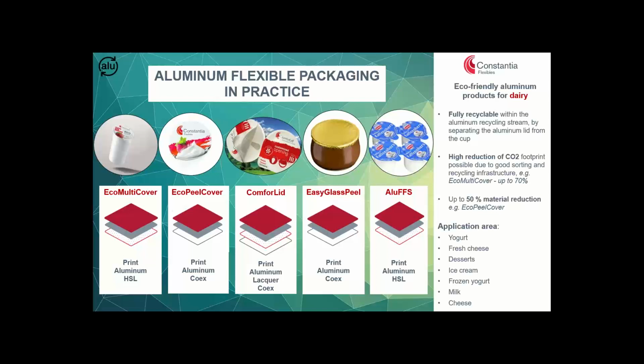So the Eco Multi-Cover is a product that has a thickness of only 30 µ, and it comes with only 4 grams of heat seal lacquer. It has very good sealing qualities against different sealing partners, so this means we have a wide sealing window here. Material reduction, as I said, is a very strong benefit here, whilst retaining the optimal functionality. It runs on conventional filling lines without machine modification. It's also suitable for toppers. Sealable against PS and PP, available embossed or unembossed.